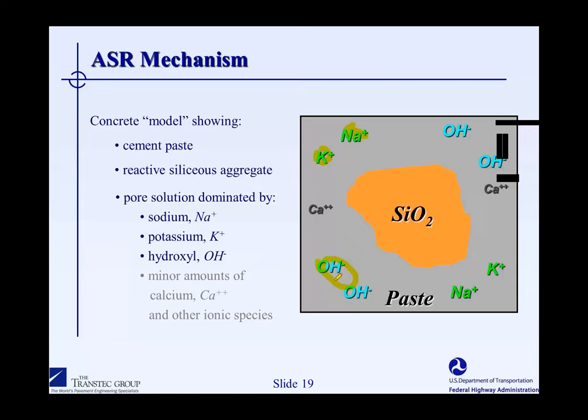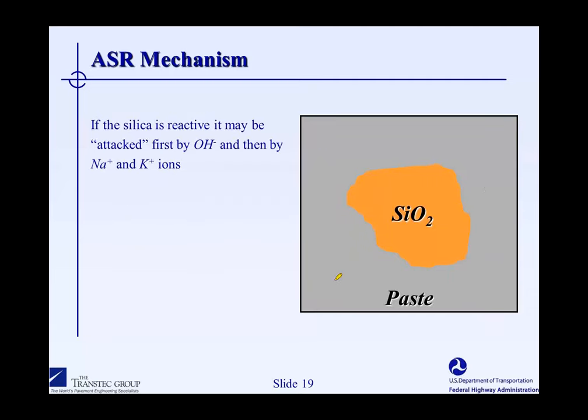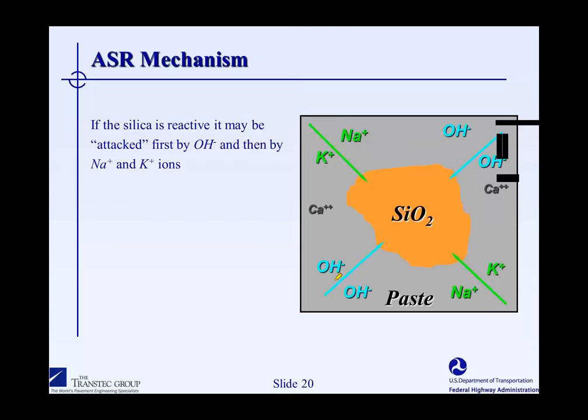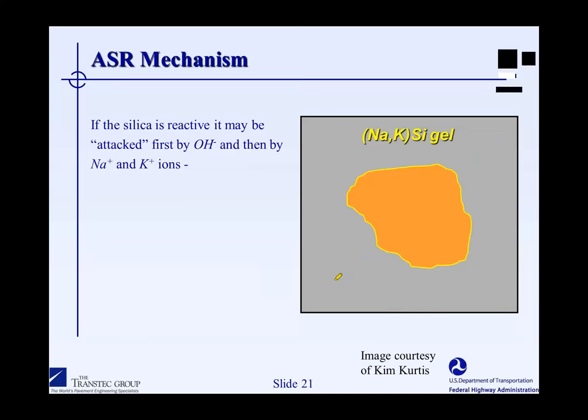The very high hydroxyl ion concentration gives rise to a very high pH in excess of 13. Many textbooks will tell you 12.5, but typically concrete will have a pH in excess of 13. Very caustic material. In actual fact, despite its name, it's the hydroxyl ions that first attack the silica. This is an important distinction, because it means that only sodium and potassium hydroxide solutions will attack the silica. Solutions of sodium chloride, potassium sulfate, or potassium chloride won't attack the silica unless there's an opportunity for those sulfates or chlorides to be converted to hydroxyl ions in the pore solution. So we really need that high pH, the high hydroxyl ion concentration, to attack the silica.